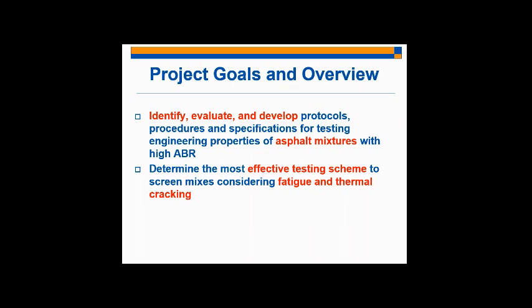So we know that with the addition of recycled content, it's typically agreed upon that adding recycled content will embrittle your material, will make it more brittle, which makes thermal cracking and fatigue primary concerns. You wouldn't expect rutting to be a primary concern if your mixture is becoming more brittle. And so this is the reason these two distresses or failure modes are the primary areas of focus.